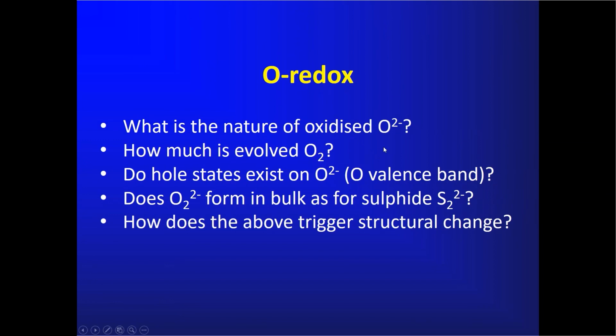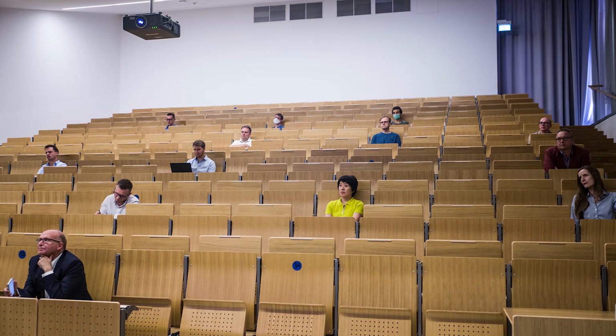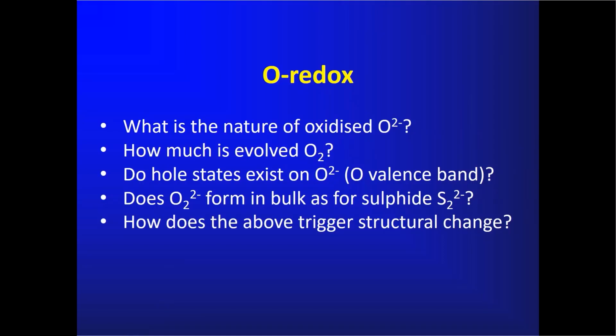So all of this means that if we're going to try to avoid that and get to ultimately a material where we can cycle at high voltage, we need to understand the nature of oxygen redox fundamentally. What happens when we oxidize oxide ions? We know that some oxygen is evolved, sometimes more, sometimes less. But can we understand what controls the direct loss of oxygen, of molecular oxygen from the surface? Do we create hole states on oxide ions in the bulk of the particles in the valence band? Do we create peroxide ions? And this would be analogous to what happens in sulfides, where we know that you can oxidize an S2- to this dimeric disulfur 2- species. Or do we form some other species? And how does all of this trigger the voltage change, the structural change that we see?